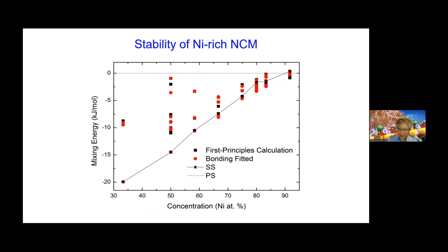As I said, there are multiple ionic configurations. We are using cluster expansion. So this NCM111, and there are multiple configurations, and we search through this atomic configuration space. And this is the lowest energy configuration. Usually they tend to be solid solution. And this PS is phase separation. When you completely phase separate, that's the reference. You have 2 or 3 separate oxide phases. And when you mix them, because of the chemical affinity of different components, you have a tendency of improving the stability.